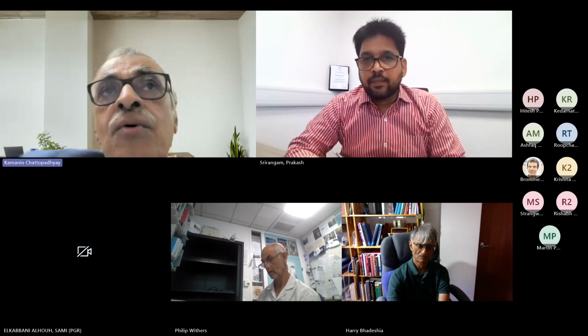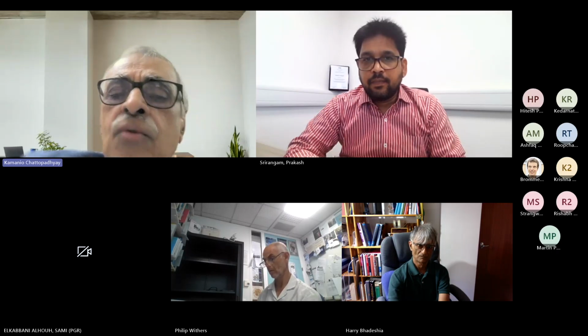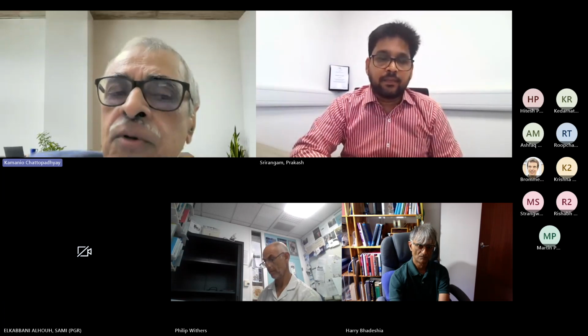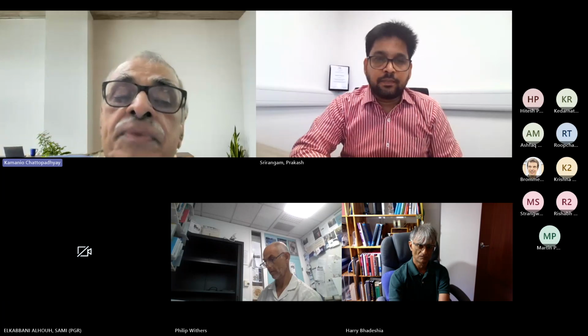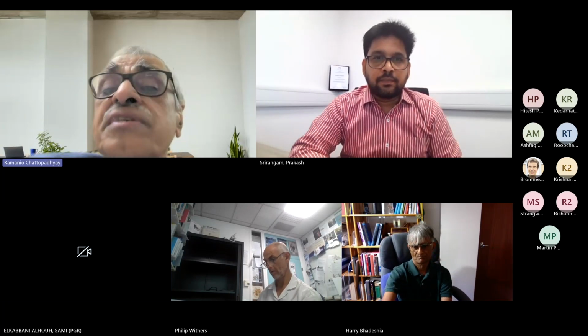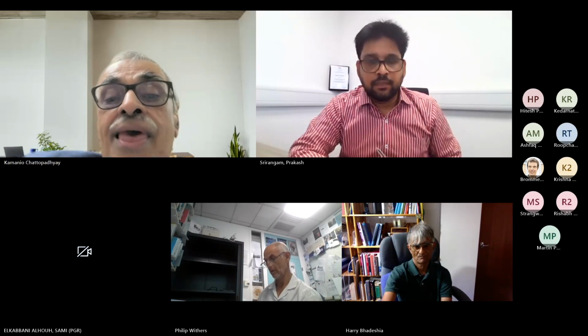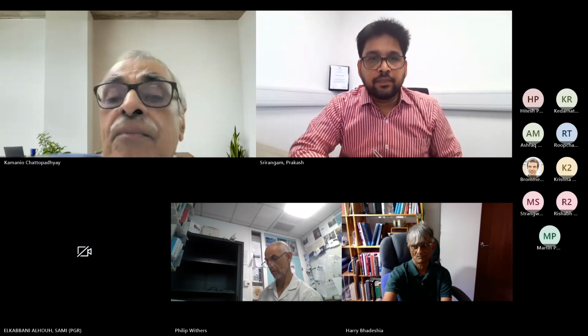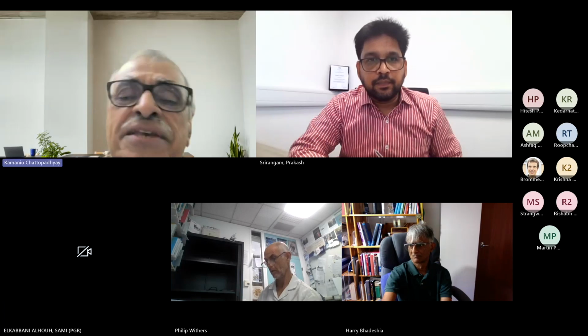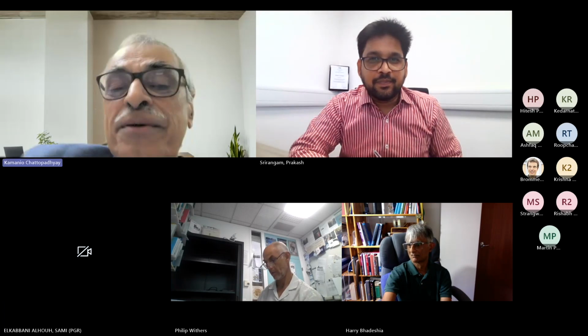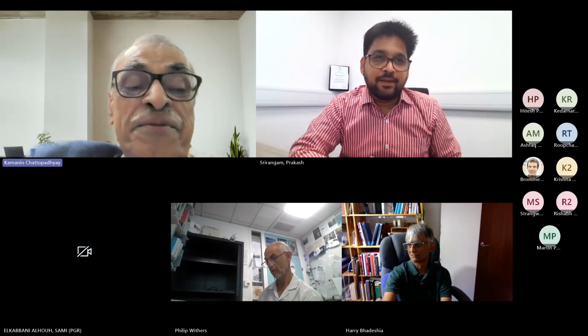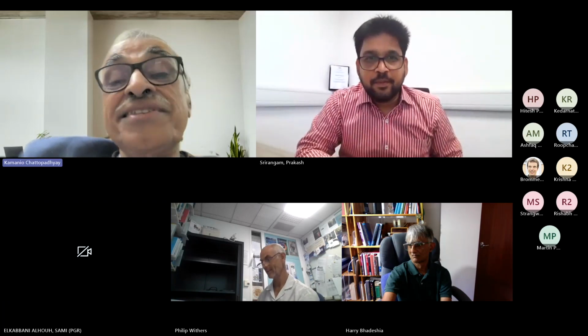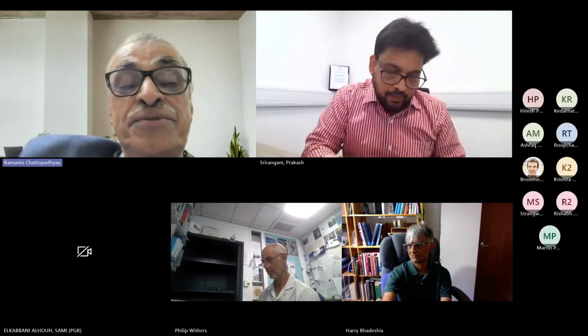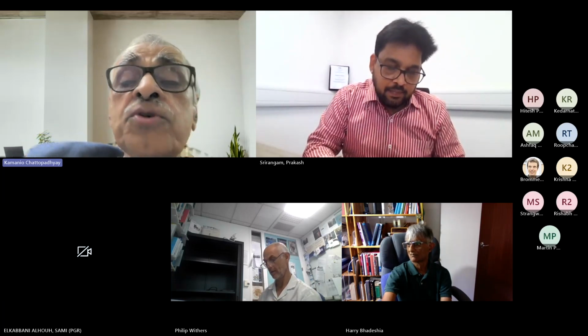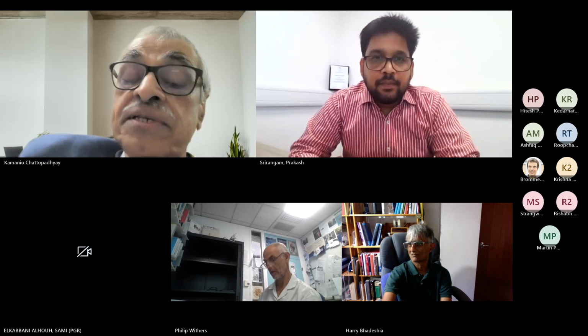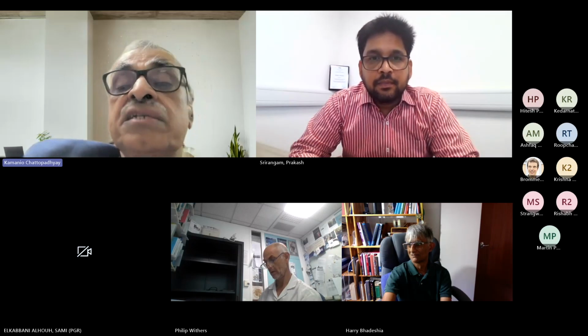And what we have found, the story of intermetallic, will publish very soon, but even if you look at the paper by the Chinese group, it is very clear the story of intermetallic is not over yet. They have shown scandium segregation inside. And they give a very fancy name to this. For me, the classical phase transformation school grew up, I never believed in those fancy names and fancy stories, but cerium is inside, scandium is inside cerium, and it produces a phase transformation. So hopefully we'll publish very soon. And then I think almost all these intermetallic L3, aluminum cerium, aluminum yttrium need to be looked at with microadditions.